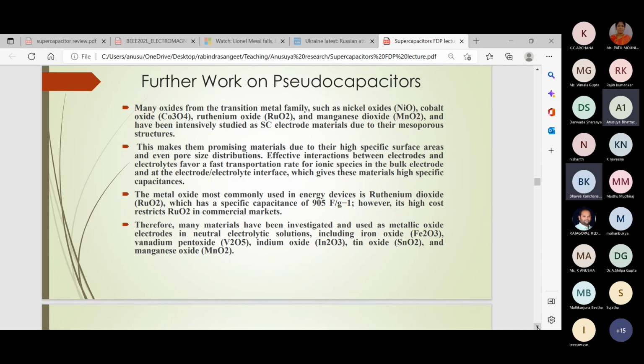So in further works on pseudocapacitors, as you said, these oxides have been studied as electrode materials because these oxides have mesoporous structures. But then you can actually create these oxides in different ways. For example, if you do a spark plasma sintering of oxides, you're going to get really thick and dense material with very few mesopores. But if you use some other method to create that oxide, you might have better mesopores. Then how do you bind them into an electrode structure? You need to have some kind of a binder. That binder itself will go and close up some of the mesopores. So there's an enormous amount of research going on as to how to increase the surface area. Iron oxide, vanadium pentoxide, which is actually a very good catalyst as well, indium oxide, tin oxide, manganese oxide, all of them are being investigated as of now.